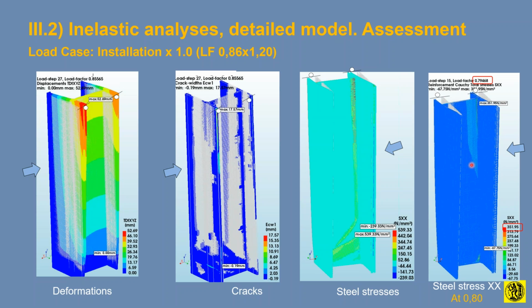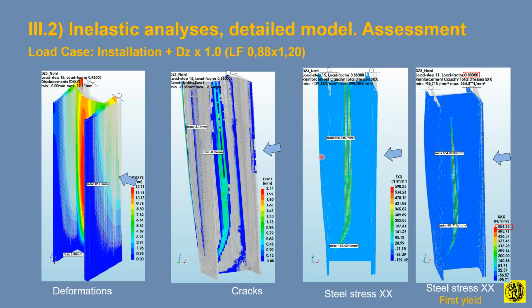And actually, if we want to see where the maximum, which is somewhere hidden in here, developed, we go back a few steps. So at the step 0.86 intensity, but 80% intensity, the stresses here are still elastic. The reason I'm going to 80 is because of the next load case, which I'm going to duplicate, to impose on this specific submergence the 3-meter differential. Okay, so let's go to the differential case, which pretty much shows a picture of the failure.